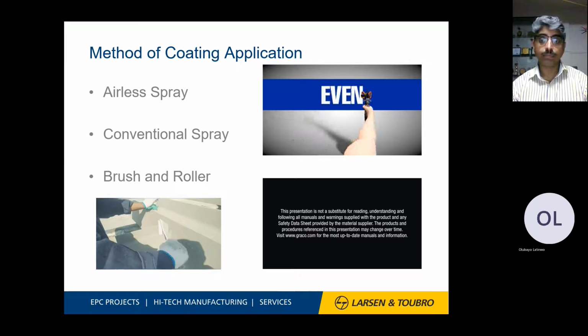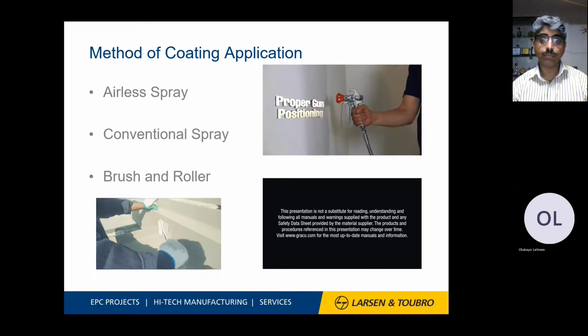Fanning the gun to direct the spray at an angle causes an uneven finish. Flex your wrist at the beginning and end of each stroke to maintain an even coat. Don't spray at an angle. Keep the gun perpendicular to the surface. To practice proper gun positioning without spraying, try moving the gun and holding it perpendicular to the surface, only about 2 inches from the wall.